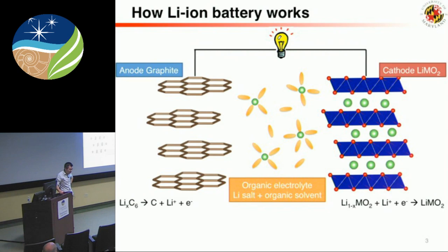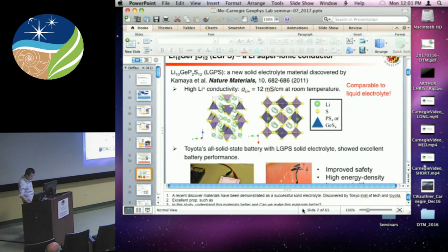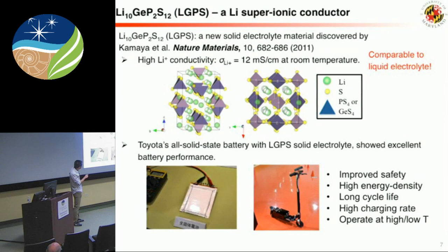So what we did here is a fairly straightforward substitution. It's something everybody would probably think about. In principle, we can do more complicated ones. I didn't show it, but in some other study, Gerbrand Ceder's work, he did some data mining to figure out which substitutions are more likely, and then you can explore more substitutions more efficiently. But technically, how do we do that? We have to statically relax the structure. Otherwise, if it's too distorted, the energy you get wouldn't make sense.